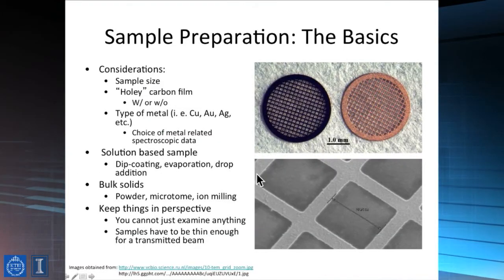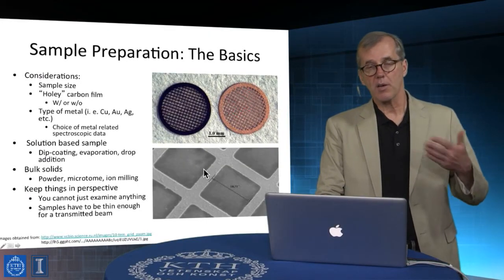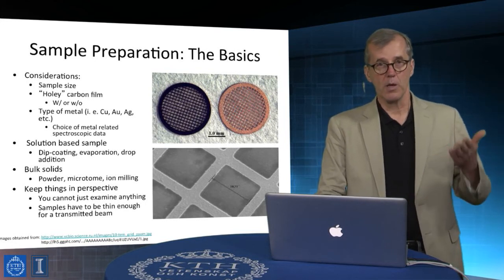All right, and there's a picture here of grids, and the most useful form of grids. So here you can see the dense metal component of this grid, and actually what's present here is an extremely thin coating of material. And various materials are used. One common one is so-called silicon monoxide, SiO. Carbon, though, is actually one of the preferred grid spanning materials. And the reason for using this is that carbon is relatively low Z, right?